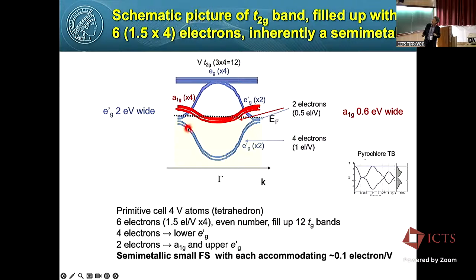And as I said, the lower EG prime band is doubly degenerate, so it contains 4 electrons. So the first 4 electrons occupy the lower EG band. The remaining 2 occupy the upper EG, but the upper EG overlaps with A1G, and therefore it should be a kind of semi-metal. And in fact, the band calculation predicts that A1G is kind of hybridized, giving a small metallic Fermi surface containing roughly 0.1 electron per vanadium.